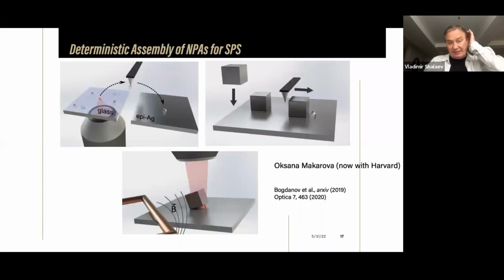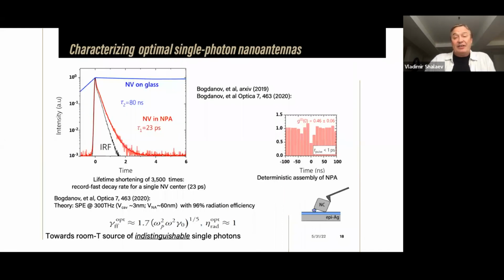But that was probably not the best way to do it. So in following experiments, we would first place the nanodiamonds on a glass substrate and pre-characterize them using this microscope, seeing which nanodiamond is really good. Then we pick up that nanodiamond with the tip of this AFM and place it on epitaxial silver. Then the same tip would push a silver cube on top of the silver so that this nanodiamond would sit exactly at the edge of this cube, where calculations show the Purcell enhancement is the largest. And in this case, we obtained much stronger results.